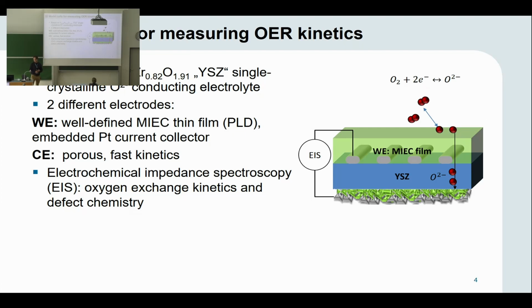Overall, we can fabricate several model electrode designs and model cell designs. However, one relatively simple design proved to be very useful if we are mostly interested in the kinetics of the surface reaction of the mixed conducting electrode. And this design is sketched here. The main part is a mixed conducting thin film, of which we investigate the kinetic properties. And this film is deposited on a single crystalline YSZ oxygen ion conducting electrolyte.